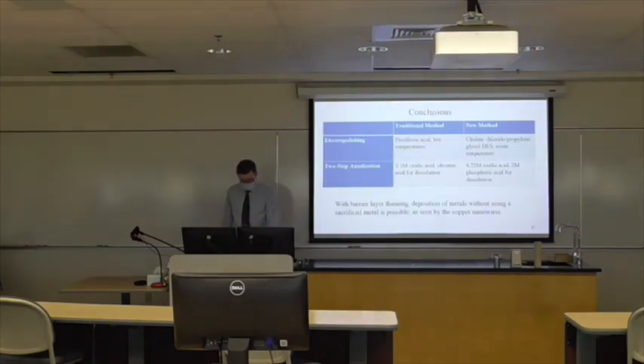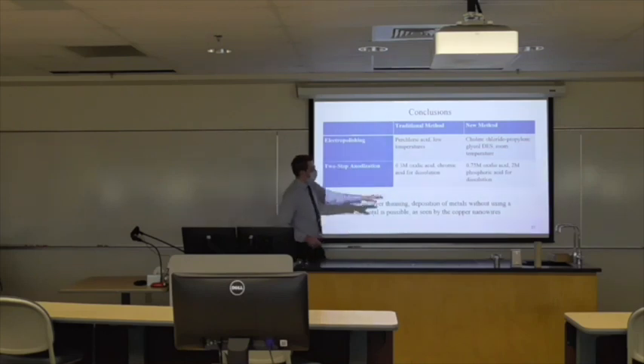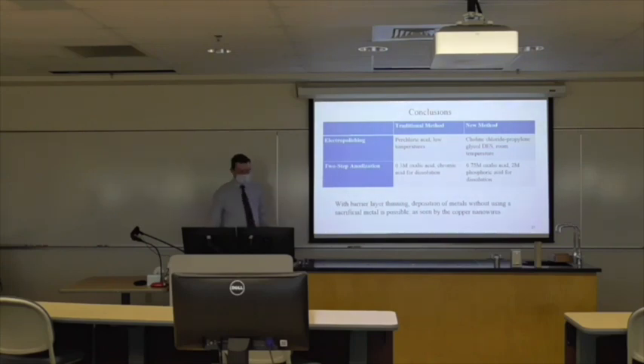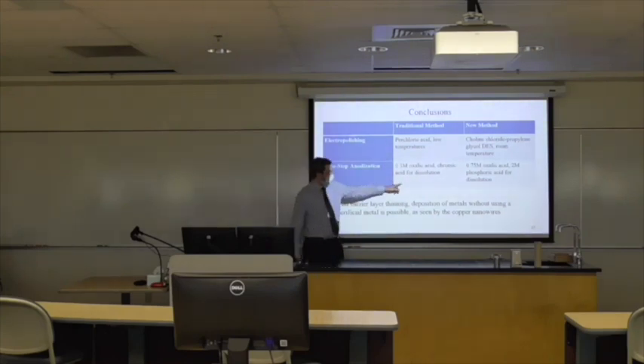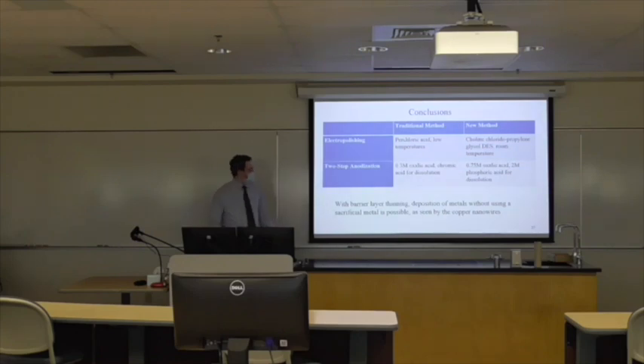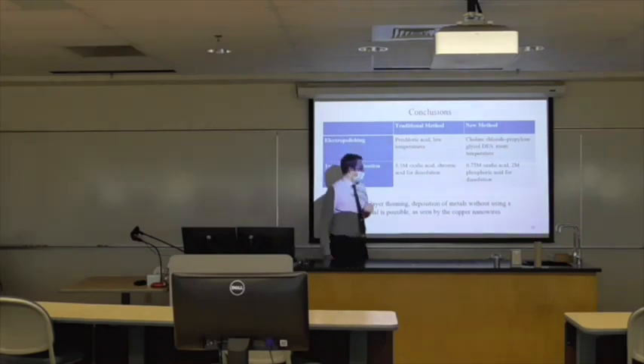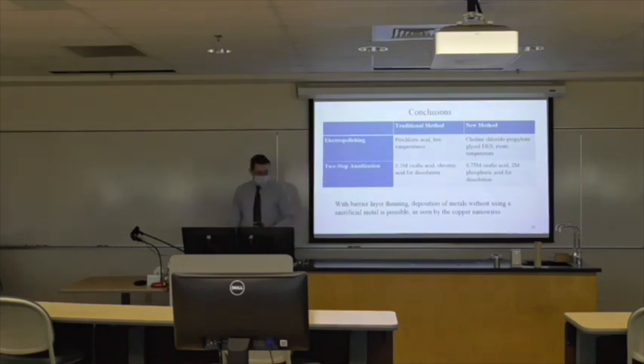So, to conclude here, the electropolishing method, traditionally used with perchloric acid at low temperatures, we're able to use a choline chloride, propylene glycol DES at room temperature to get a good polish. Using a two-step anodization process, generally 0.3 molar oxalic acid is used, as well as chromic acid for dissolution. We use instead 0.75 molar oxalic acid and 2 molar phosphoric acid for the dissolution. But lastly, with the barrier layer thinning method, the deposition of metals without sacrificial metal is possible. And we showed that with the copper nanowires, that we can deposit metals into the pores and produce these nanowires.